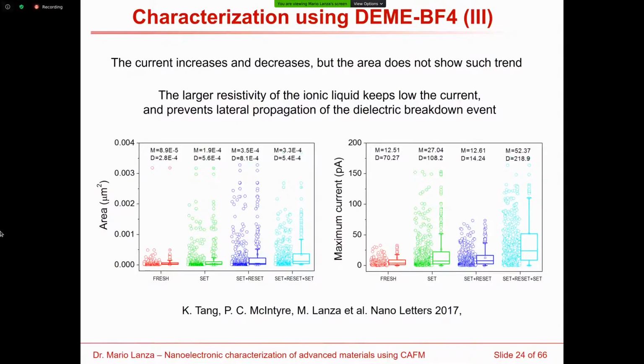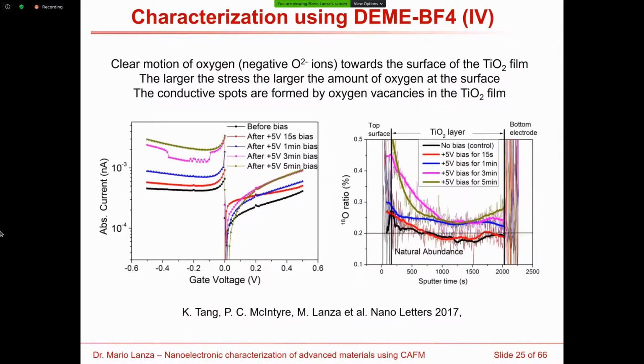Actually, this method also allows us to apply chemical tests. So here you can see one very interesting oxygen detection with NanoSIMS, in which, depending on the time that we apply this electrical stress, we can see that when the time increases, the density of oxygen at the surface also increases, which means that this increase of the conductivity is related to the formation of oxygen vacancies inside the dielectric. This was published in Nano Letters in 2017. You can see more information in that paper.